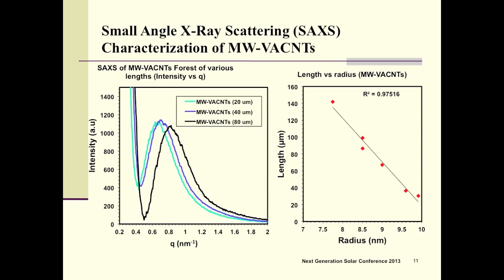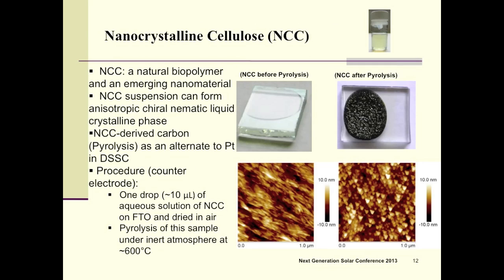And we propose that the 20 micron carbon nanotube length electrode has higher specific surface area available to reduce the triiodide ion to iodide ion, and all the characterization supports that this particular tube length gives us our optimum efficiency. We also did work on nanocrystalline cellulose, which is a natural biopolymer, and it has very fascinating